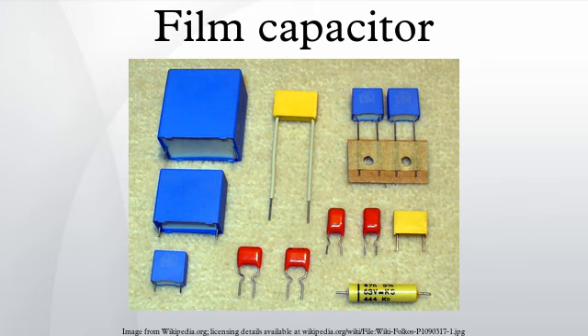In addition to their excellent electrical properties, PPS film capacitors can withstand temperatures up to 270 degrees Celsius without damaging the film quality, so that PPS film capacitors are suitable for surface mount devices, and can tolerate the increased reflow soldering temperatures for lead-free soldering mandated by the RoHS 2002 EC directive. Cost of a PPS film capacitor is usually higher compared to a PP film capacitor.